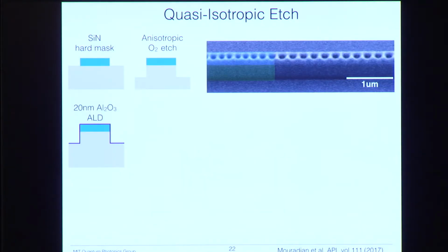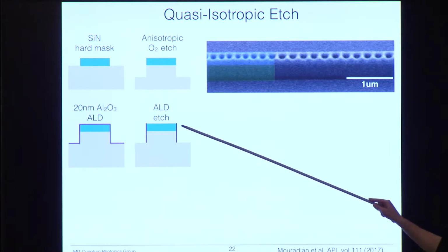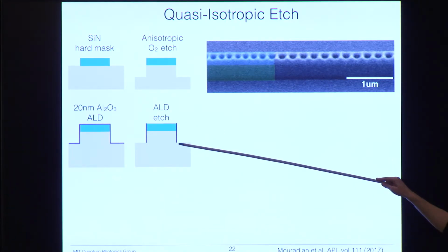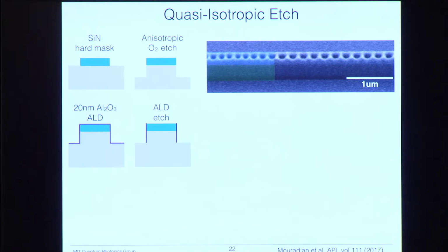We then cover everything with 20 nanometers of aluminum oxide with atomic layer deposition. This allows us to cover everything and also cover these little holes conformally. So these holes are about, now I forget, it's been a while, 200 nanometers, let's say, or smaller. So we need something that will conformally coat also into the holes. We then do a breakthrough etch to etch off the top surface and this surface here while maintaining coverage of the side surfaces. We then do a second anisotropic etch just to give us a little bit more diamond exposed.